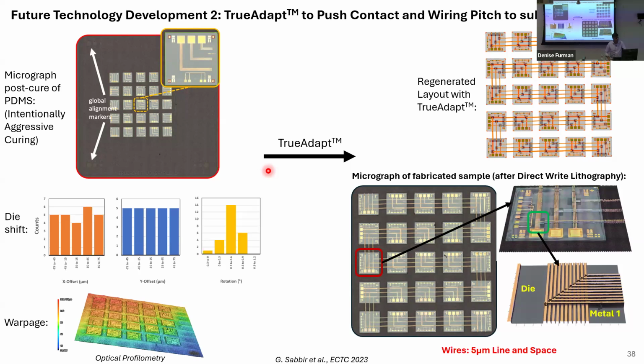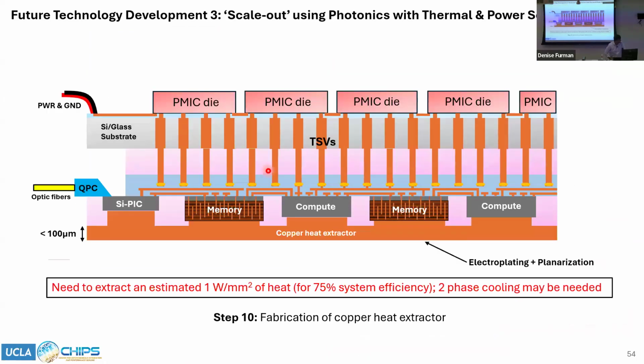On maybe slide 54 or 55, where you backfill with copper for thermal management, you make the argument that if you have local heating of one of these components, the distortion is distributed. Does that make any assumptions about the interface between the upper heat extractor and that particular component? Are those mechanically rigidly coupled to one another? Yeah, they're rigidly coupled. So if you're actually simulating this, there will be a slight bend in this. But the idea is it's compliant enough that nothing breaks. Gotcha. Excellent. Also, this is an idea, it's not something yet.